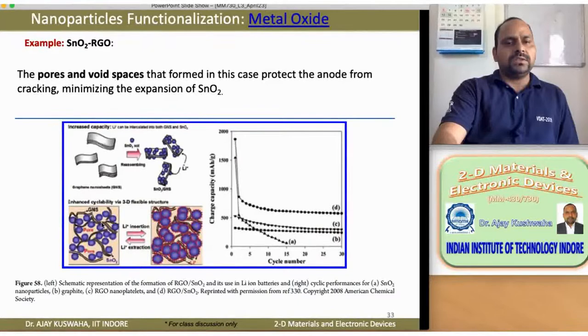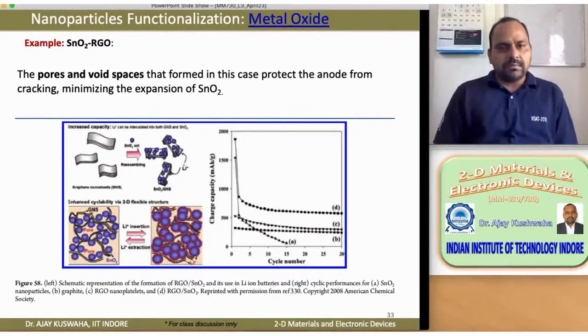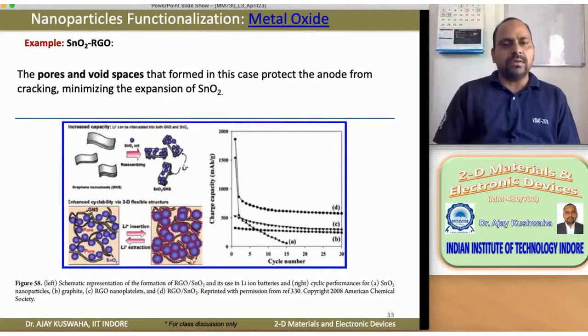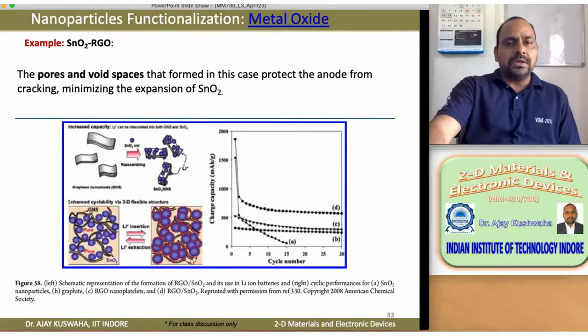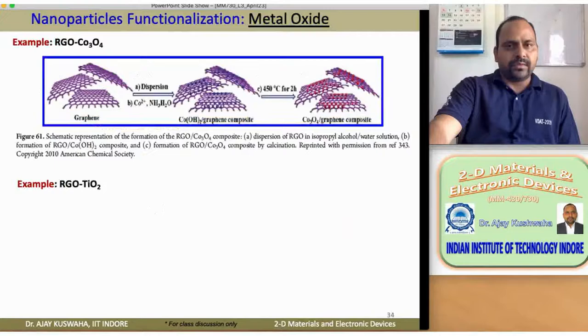So see this black color. These are the reduced graphene oxide sites, and this is SnO2. So whenever there is a pore or any other area, this graphene nano ribbon is going to fill that area. And they have investigated the charge and discharge cycle as well as durability of this battery electrode, and they found that this is a reasonably good solution to resolve that kind of issue.